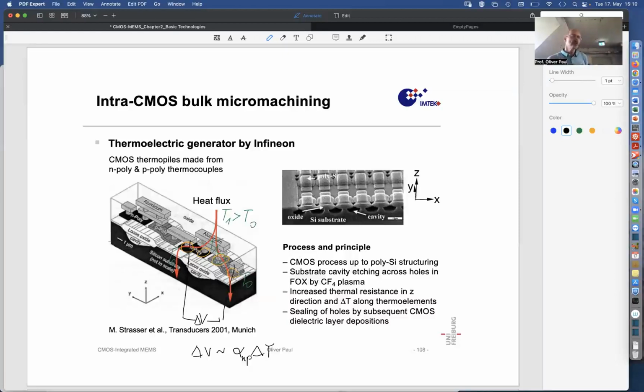That's because of the temperature gradient in the material. There's an electric field generated by the temperature gradient with the Seebeck coefficient, or thermal power. So let me call this as it is, Seebeck coefficient, or thermal power. In English, they prefer to use the name thermal power, the thermoelectric coefficient. So this electric field generated in the P polysilicon will be in the opposite direction. If the two polysilicon were the same, the two field directions would be opposite, and so the voltage difference in one direction would be compensated by the voltage difference in the other direction. So we would measure delta V equals 0.